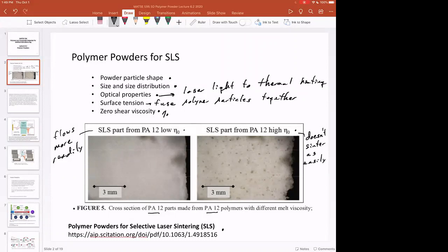And you can see that because you have optical defects. So these are either holes or unsintered particles. You don't really get good coalescence of the material if you have a high viscosity, because of course it doesn't flow as well. Where here you have very uniform coalescence of the particles because the viscosity is lower. So as you're sintering these things, you get good coalescence within your part, and the part looks good. Because of course, any of these optical defects have the chance to become a stress concentration defect or some other defect that changes the properties of the part.